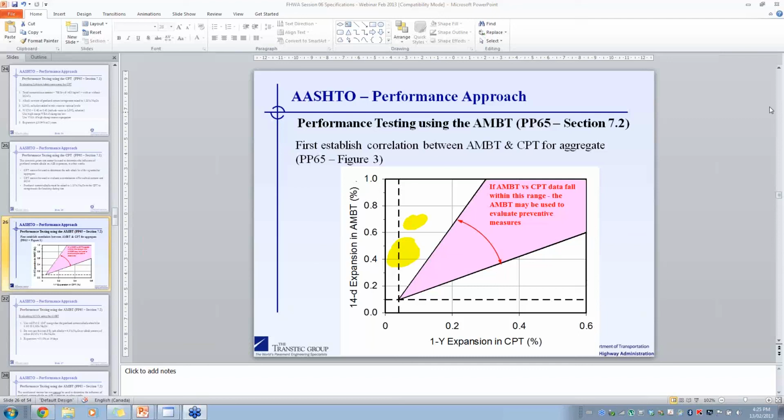We do quite a lot of work where we put parallel specimens on our sites up in Canada, and our colleague Kevin puts the same concrete mix on his site down in Texas, and there can be a factor of 6 times difference in the time it takes for expansion to occur because of the differences in climate. And that's not even allowing for any differences in composition of the concrete.